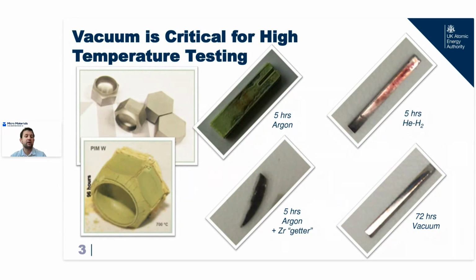So I've spent a long time working on tungsten. The tiles you see on the left here are candidate plasma facing tiles for future fusion reactors. But unfortunately, tungsten loves oxygen. No matter what you do to it, whether you test it in an inert argon atmosphere, a reducing helium hydrogen atmosphere, or if you stick other metals like zirconium into your vacuum chamber to do your very best to soak up all the oxygen, your tungsten will eat it. And when you have the 2 micron irradiation damage layers that we've just seen, that you're really interested in testing, this oxidation ruins them.